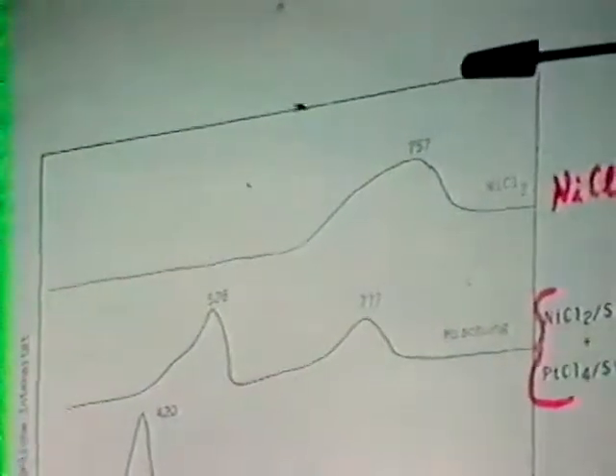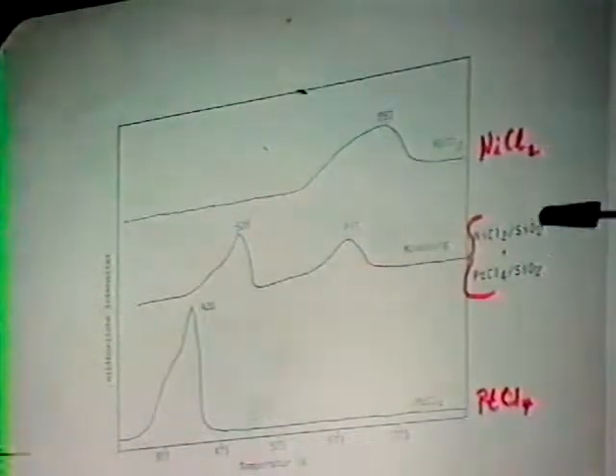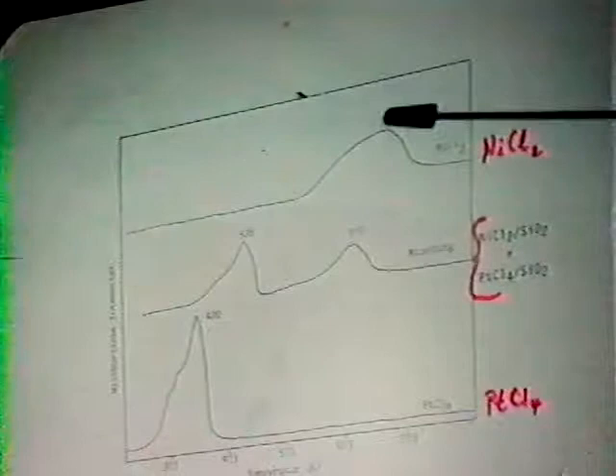If you look at just the reduction of the precursors, this is reduction of nickel chloride somewhere around 750 degrees or so. Reduction of platinum chloride in the bulk state can occur around 400, 420 or so. And if you take a pure nickel or pure platinum catalyst, nickel precursors on silica, platinum precursors on silica, you get some change in the reduction point of this precursor, but you see that they are still quite separated, one from the other.